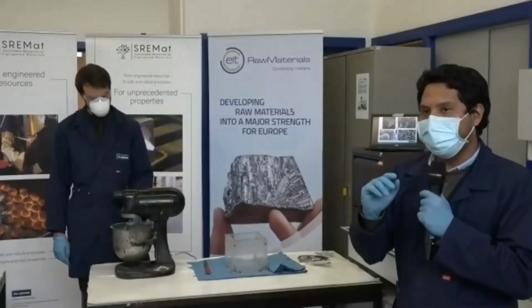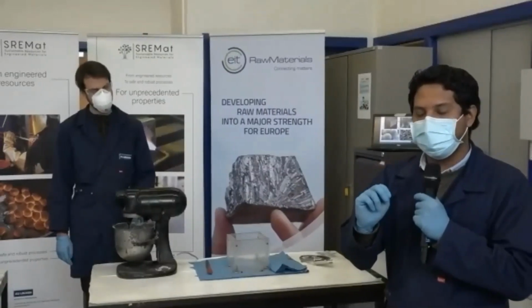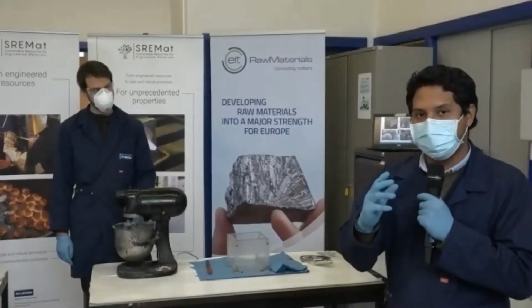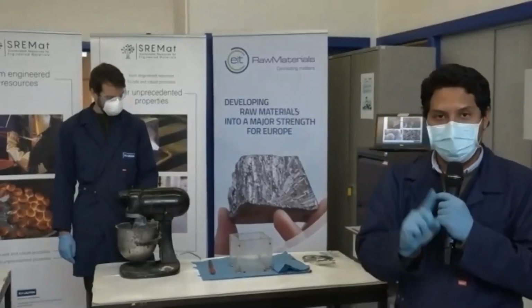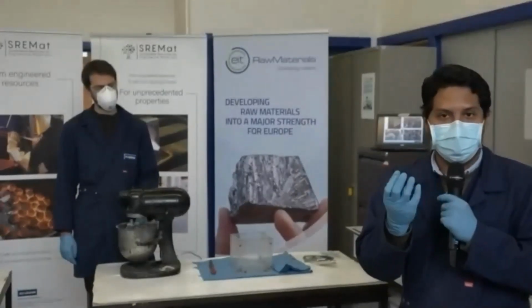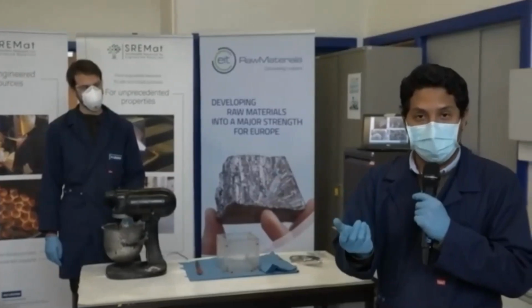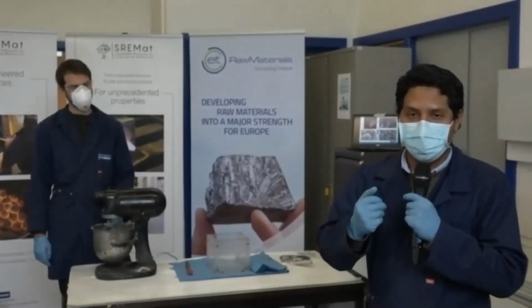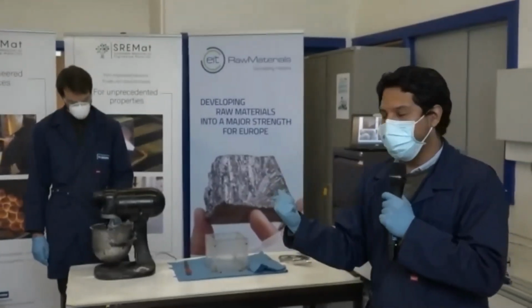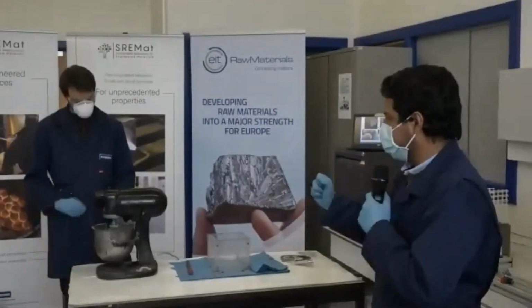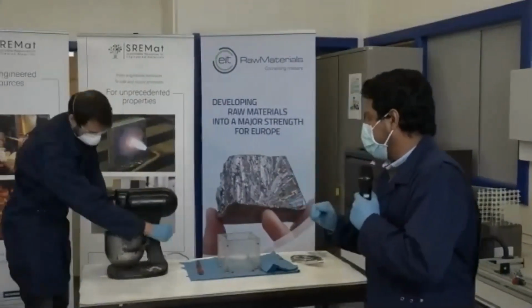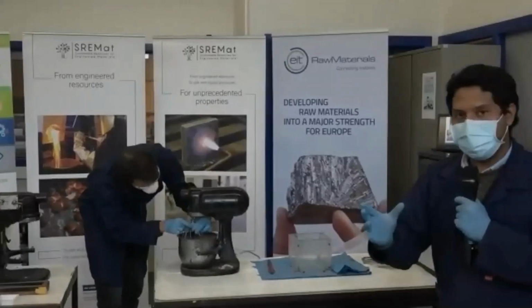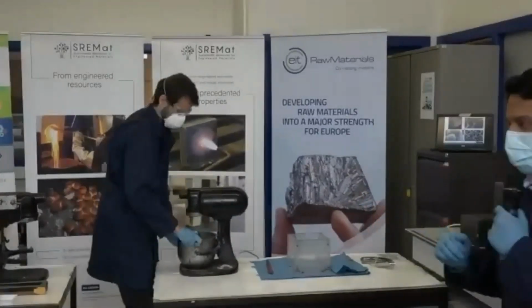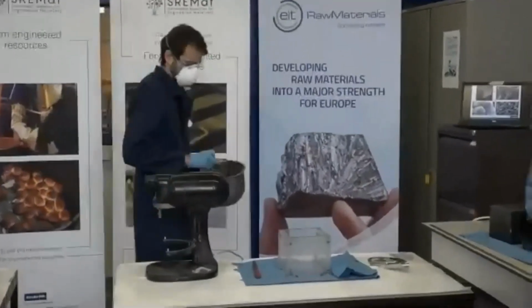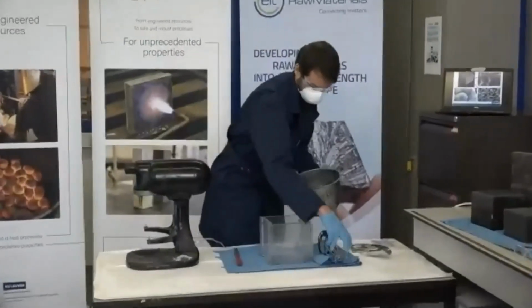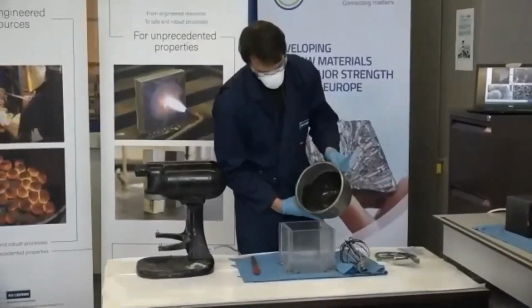Well, there are a couple of reasons, but the principal is that we would like to create a porous structure. As I was telling you in the step before, we already create a little bit of a foam inside of the paste because of the addition of the surfactant. And what we are doing right now, Tobias will stop it. What we are doing right now is that that aluminum in the alkali system will react, and then we will create hydrogen gas inside of that paste.